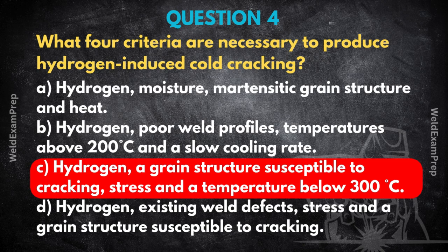People might think their consumables are dry, or they might not realize how much impact surface contamination or humidity can have. And because it's delayed, they might finish the weld, it looks fine, and they move on, unaware a crack is developing hours later. A really important reminder about diligence.